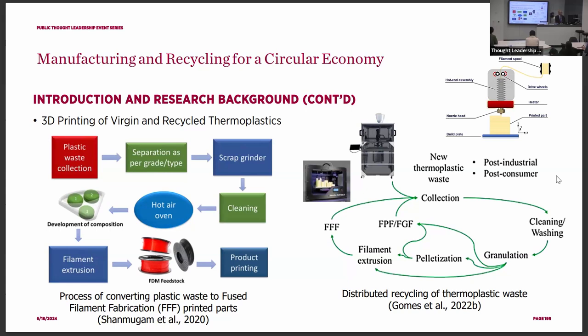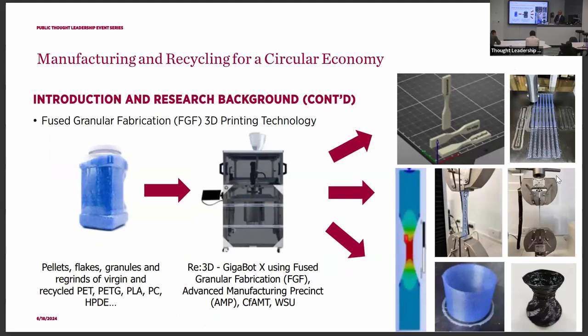That's what we do for 3D printing of recycled plastic waste using fused granular fabrication technology. That's the machine we use here. With this fused granular fabrication technology, we start from pellets, flakes, granules and other types of materials. In our research, we can do recycled PET, recycled PETG, PLA, PC, and HDPE, and then we put them into this machine.